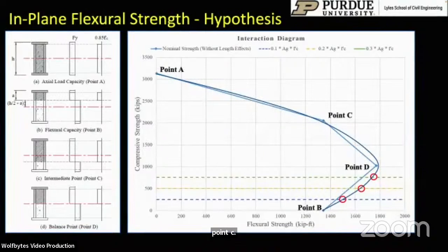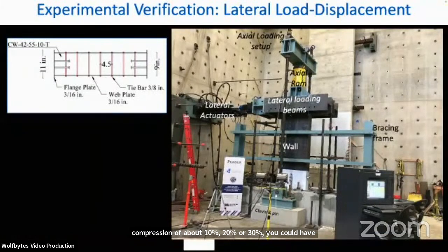You can develop the PM interaction for this composite section, kind of similar to the way you do it for reinforced concrete, but using composite section principles, and those have been identified here. So depending upon if you have an axial load in compression of about 10%, 20%, or 30%, you can have different in-plane flexural capacities, which we'll talk about in just a moment.